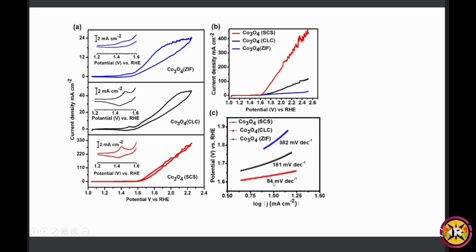I have observed that the Tafel slope value for SCS, the red one, is 84 millivolt per decade. So that is quite less than the other two. If the Tafel slope value is lower, then we can say the forward rate of reaction is higher. So from electrocatalytic activity also, we observe that Co3O4 SCS is showing higher current density, lower overpotential, and lower Tafel slope value. That's why, due to the presence of higher oxygen vacancy, it is showing good catalytic activity.